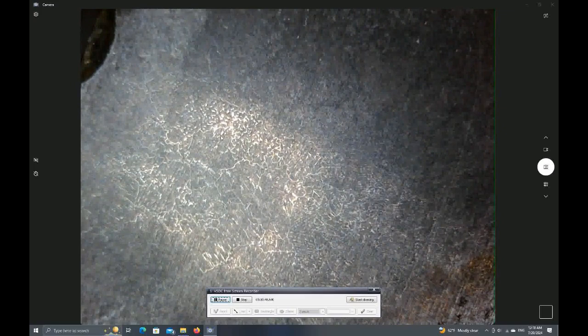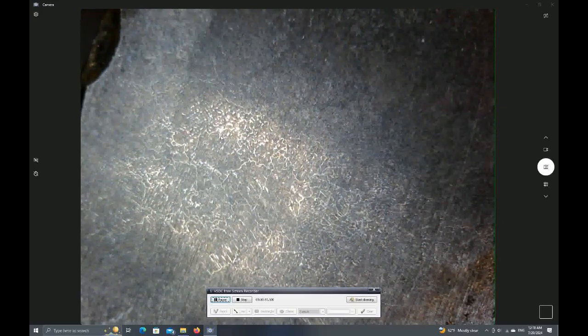So this is, again, yesterday's ingot, 18th July 2024, and it was a bit remarkable in that I did not have enough glass in the charge, and therefore during heating, while the metal was hot and molten, the glass, my best explanation is that the glass wicked up the walls of the crucible, and it did so uniformly all the way around, and therefore that left an eye of about 2 centimeter diameter completely exposed in the middle, where the local atmosphere inside the crucible could contaminate the ingot.